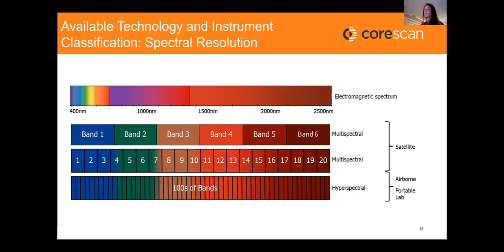A system is referred to as multispectral when it collects targeted non-continuous bands, typically about 10 bands, and they might have bandwidths of about 100 nanometers. While a hyperspectral system is a term used for the collection of continuous narrow bands at approximately 10 nanometer bandwidths, and is generally used more for airborne and portable and lab systems.